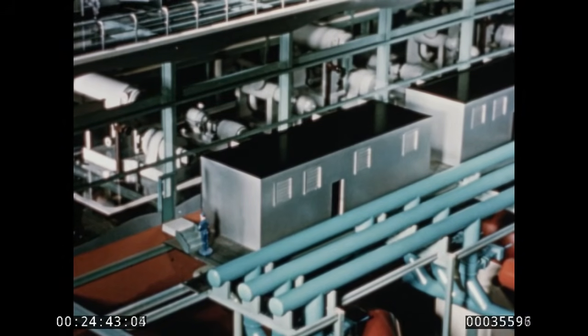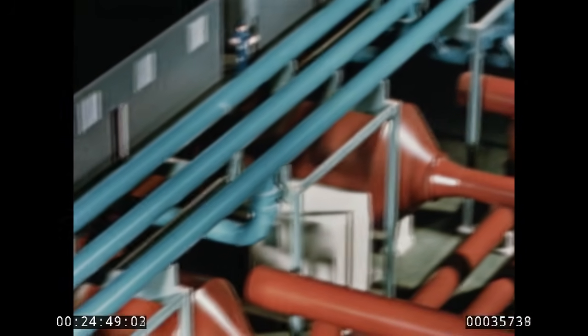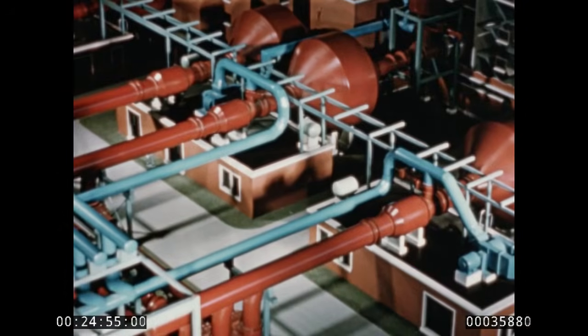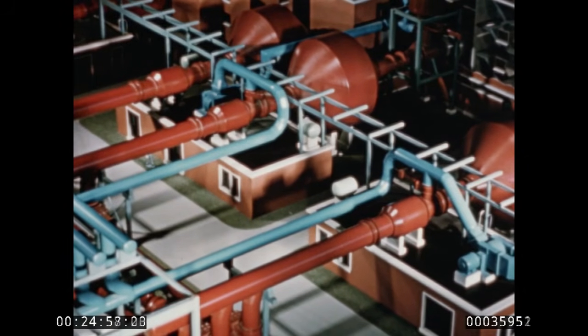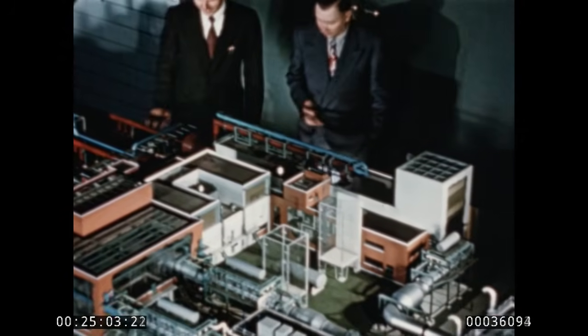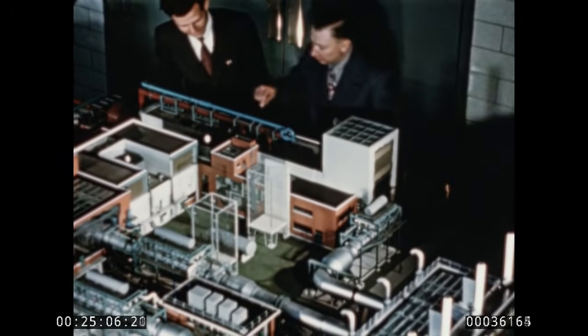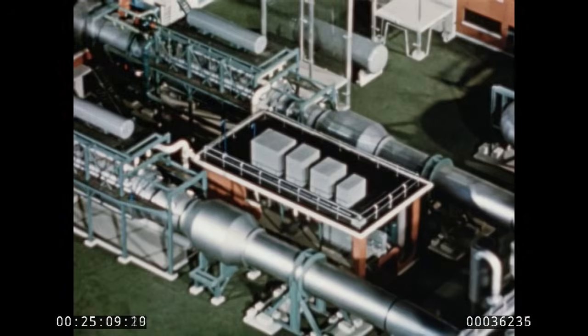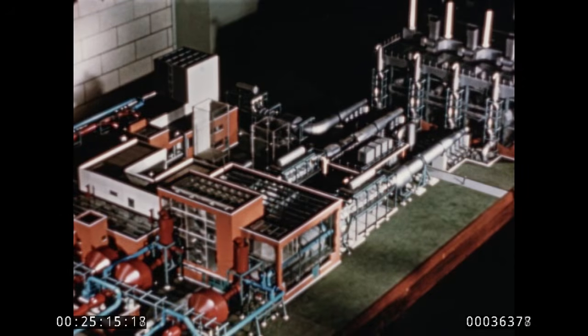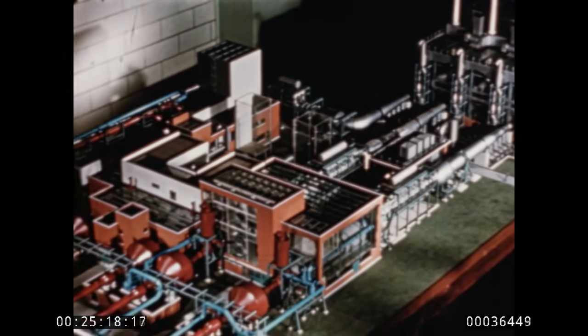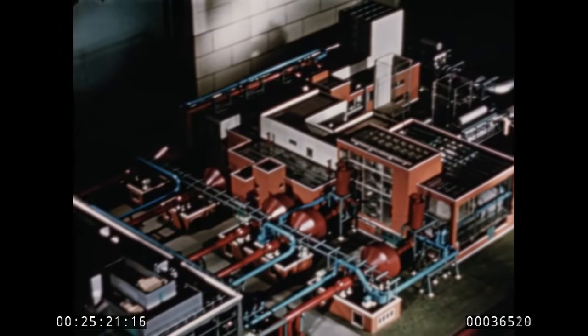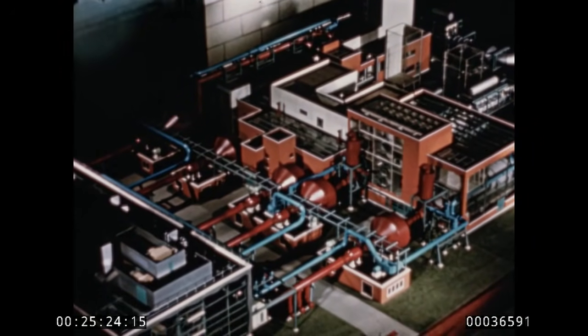During tests that range from 200 degrees to minus 75 degrees, the smooth, hard, clad surfaces of the dehumidifying and refrigeration units, as well as the piping, eliminate the danger to valuable jet engines from flying rust or flakes of paint or sprayed-on metallic coatings. Nickel steel, specially developed for low-temperature service, and one of many available special-purpose backing materials, assures positive resistance to sudden, violent pressure and temperature changes. That's why Navy engineers specified clad steel for the high-priority work of this laboratory.